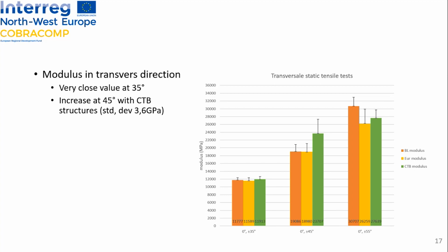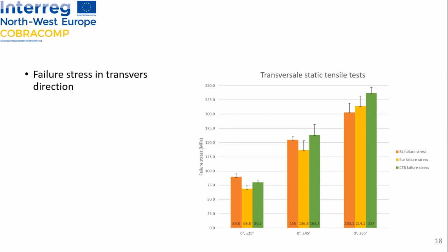But unfortunately, this result is not really correlated with the result at 55 degrees. So for the failure stress in the transverse direction, the multi-layer interlock reaches close to the baseline at 35 degrees and obtains better results at 45 and 55 degrees. So maybe the linkage of bias yarns could bring improvement of behavior.